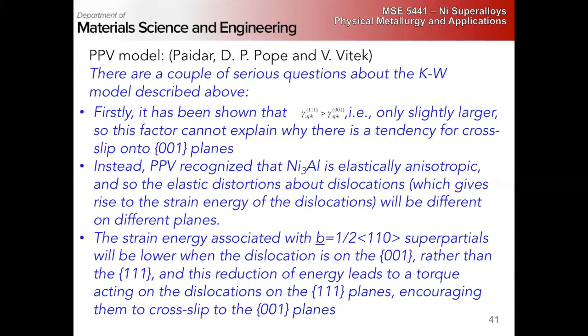But what the folks behind the PPV model did is they essentially did that, and they came up with calculations that show that the strain energy of the superpartials becomes lower when the dislocation is on the 001 rather than the 111. So it's not the antiphase boundary energy, but the elastic energy due to the neighborhood distortions caused by the core of the dislocation, right? So this reduction of energy actually gives you a torque acting on the dislocation, a twisting moment acting on the dislocation, which then encourages the cross-slip, right?